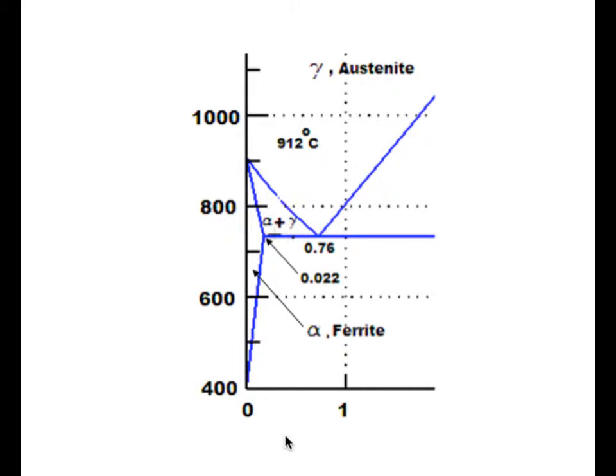So what happens now when we want to temper this martensitic structure? We increase the temperature and come up into this area somewhere. And then we see in the phase diagram that we are in the region here where we should have ferrite with this carbon content, and we should have cementite with a carbon content of 6.7%. And what's going to happen? What's going to happen is that we're going to precipitate cementite particles. So carbon is going to go from the martensitic positions, and then we go to the cementite particles. It means that we get small cementite particles, and around them there will be ferrite with low carbon content.